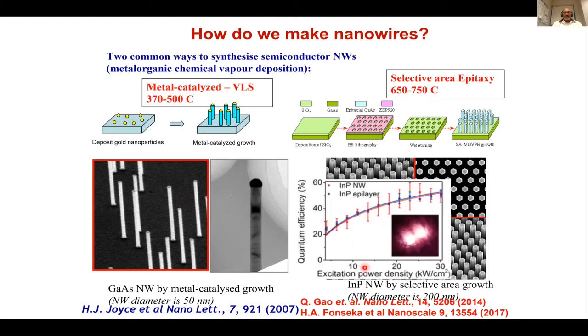We've looked at the light emission from these indium phosphide nanowires by exciting them with a laser pulse and looking at the light coming out. Then we quantified the quantum efficiency of the light emission from these nanowires and compared it with the epitaxial layers, the two-dimensional layers which we grow. They both show very comparable quantum efficiencies, indicating that they show excellent performance despite the large surface area of these indium phosphide nanowires.